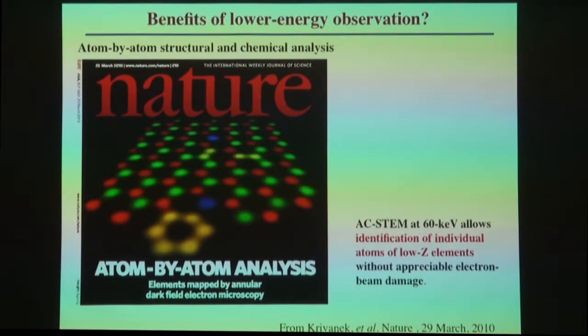In this case, it's a boron nitride sample, and there's a little bit of some silicon and some oxygen, I think. There's the oxygen, there's a couple of stray silicon atoms, and he was able to identify the boron, the nitrogen, the oxygen, and the silicon atoms one by one. The sample just sat there for long periods of time at 60 kV without appreciable beam damage. That's okay if you're in the market to look at two-dimensional materials like boron nitride or some of these other chalcogenide materials, molybdenum disulfide, for example, again.